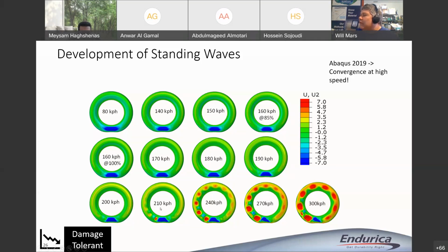But once you hit about 210 kilometers an hour, you start to have some really interesting dynamics, because in a tire, you get what's called a standing wave, where the rotation speed of the tire corresponds to some natural frequencies in the structure. And you actually, at steady state, get these standing waves, very destructive to the tire, because, prior to a standing wave, you really have one deformation cycle per tire revolution. Once you get a standing wave, you get multiple cycles of the rubber per revolution of the tire. Very damaging, and this is where you'll see a large amount of self-heating.